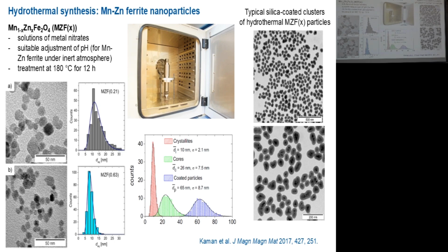I would say that the main advantage is the ease of preparation, that even anyone without proper chemical training can do this very easily. There is no special manipulation. Also, the amount produced in a single batch can be quite good. In a 50 milliliter autoclave, we usually prepare around half gram of material in a single batch. These particles are typically very well crystallized. There are no issues with some amorphous components, and the crystallinity is high compared to other methods. In this case, no surfactants were involved, so you will isolate at the end just some inorganic material, not burdened with some organic components.